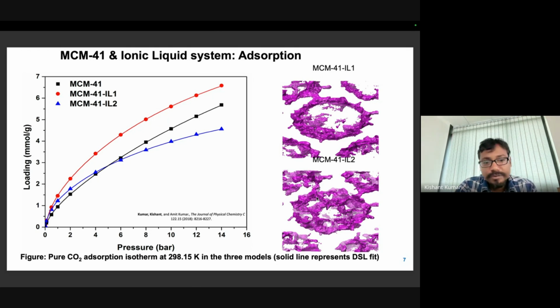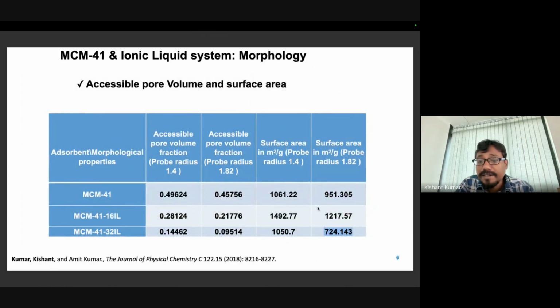So here, we have tried CO2 adsorption in such a mesoporous material, and this loading with respect to pressure is benchmarked or tested with the real experiment also, and we observed a good match between the experiment and our developed model. So we have developed the model, we have calculated the CO2 loading inside our model, and the model gives the best match with the real experiment. In this way, we validate our model, that our model is accurate and mimics the result of the real experiment. So we can see here, upon impregnation of 16 pairs of ionic liquid inside the mesoporous material, which was really giving a high surface area over here.